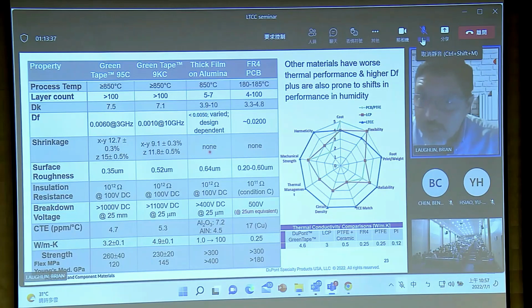There's not really any shrinkage in thick film on alumina. There is in the Z direction, but not in the XY, so that makes it slightly easier. And you can process things on aluminum nitride, which has very good thermal conductivity, if you wanted to. It's a little bit more difficult. It takes nitrogen firing, a little bit more care. But you could do thick film on alumina, though you're not going to get a planar device.